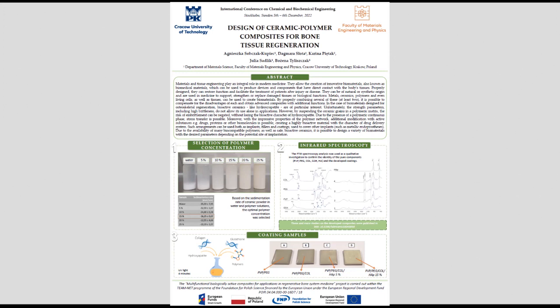Those coatings we obtained under ultraviolet light for 4 minutes, and then, in order to avoid excessive sedimentation, sedimentation weight tests were carried out on the Multiskan MS-20 device, where a polymer concentration of 15% was found to be the most optimal for our materials. We measured concentrations from 5% to 25%. Also, using infrared spectroscopy, the purity of the compounds was analyzed, as you can see in the second picture. All this research was carried out within the framework of the project Multifunctional Biologically Active Composites for Application in Regenerative Bone System Medicine. And that's all about the poster of my friend.